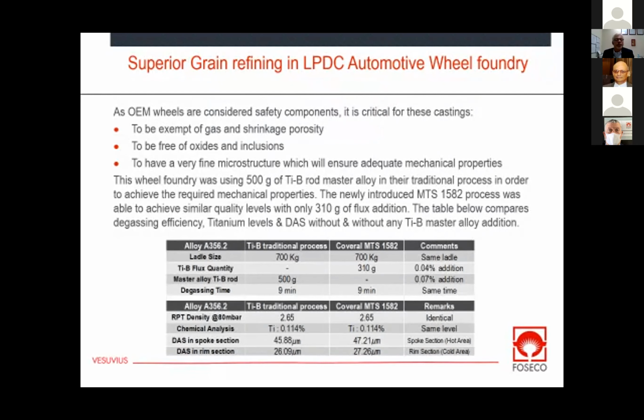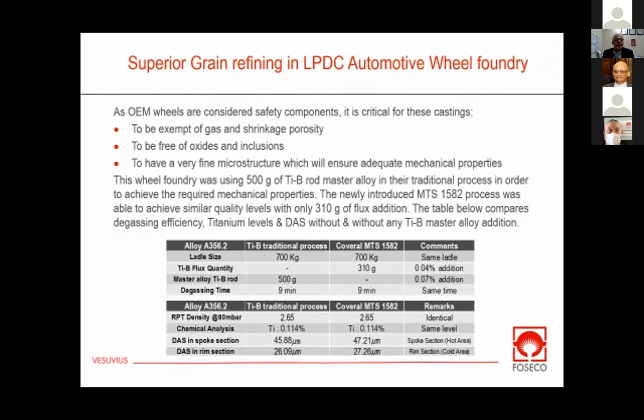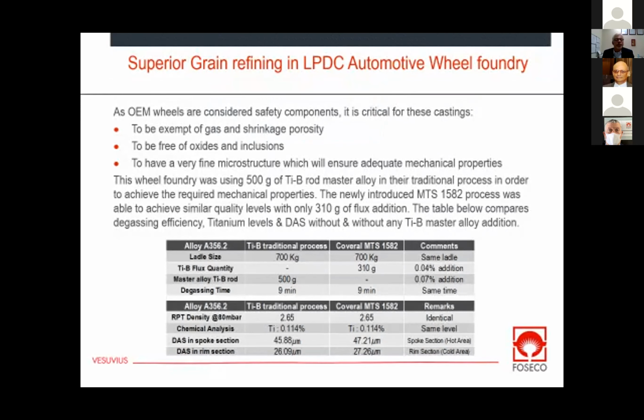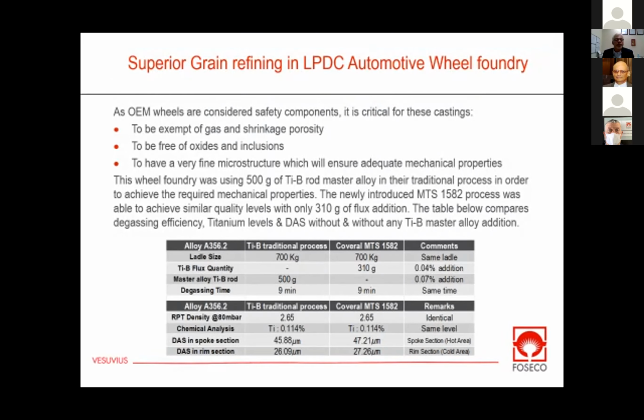They made a certain number of wheels, which they heat treated using the standard T6 heat treatment. Then they took samples from the spoke, from the hub, and from the rim of those wheels, and they measured the DAS, because even though DAS is not directly related to grain refining, dendrite arm spacing is a critical parameter of the wheel manufacturing process.